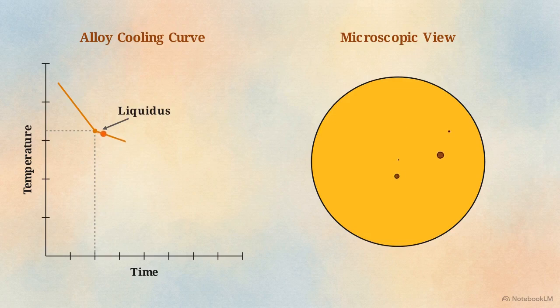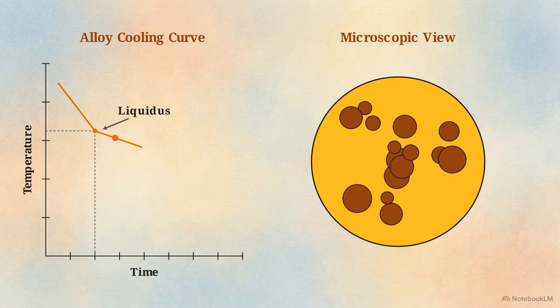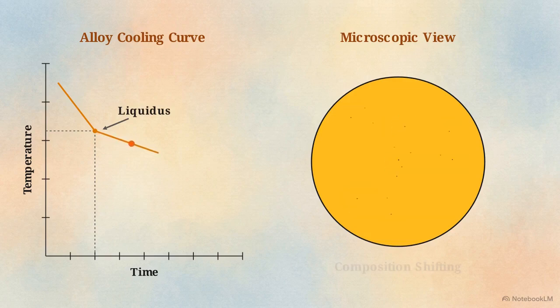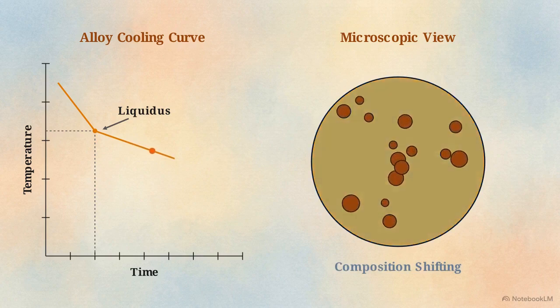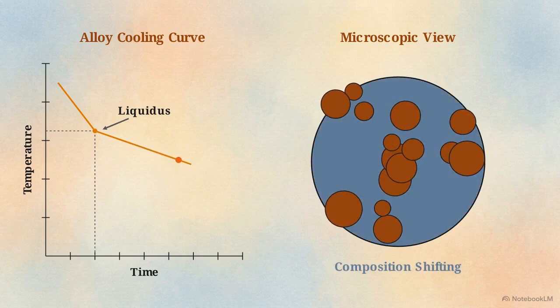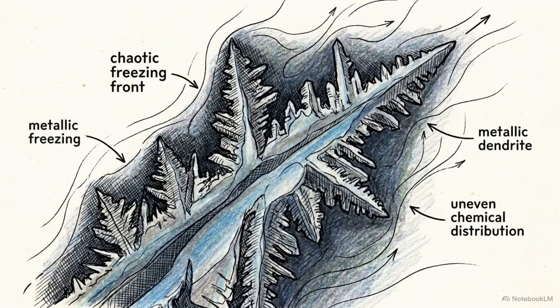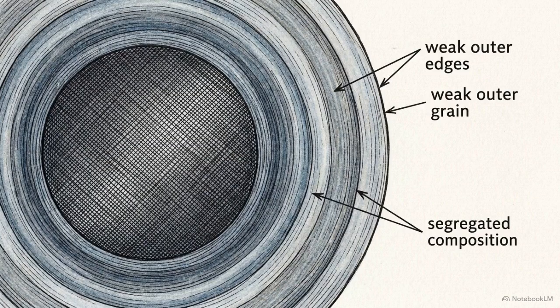The metal freezes gradually. As the alloy cools down that slope, the element with the higher melting point solidifies first. That means the chemical makeup of the liquid that's left behind is constantly shifting, changing the freezing temperature along with it. This creates a severe microscopic danger called coring. Because the freeze happens faster than the atoms can evenly distribute, each metallic grain develops a weaker, segregated chemical composition at its outer edges compared to its center.